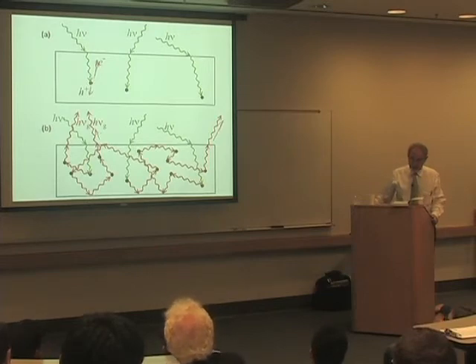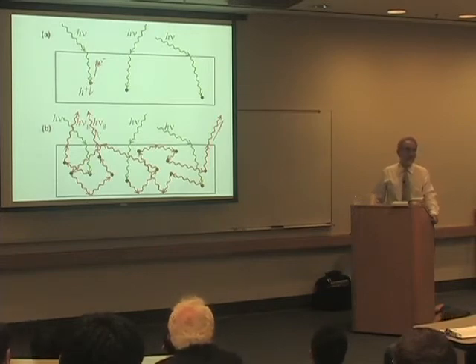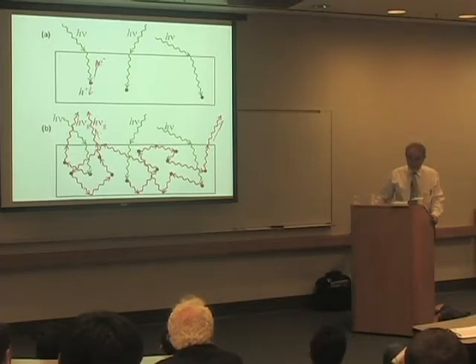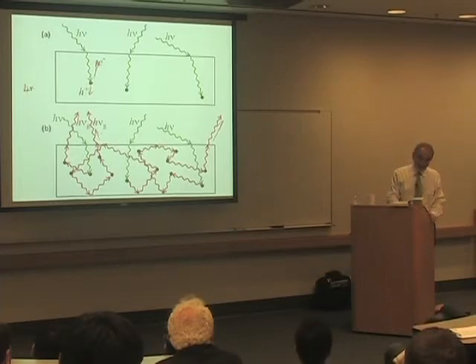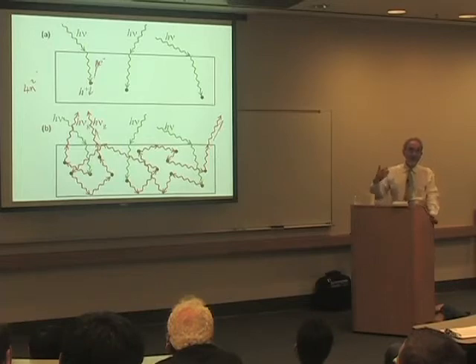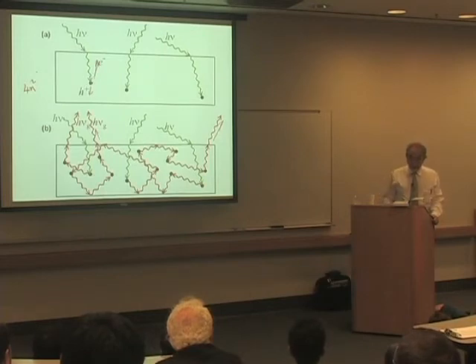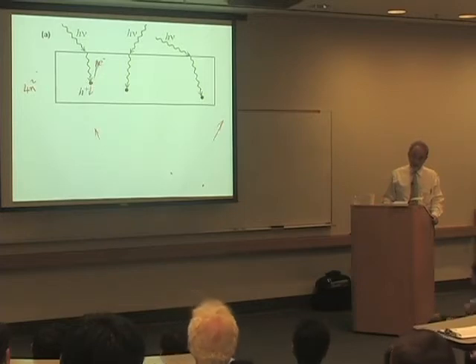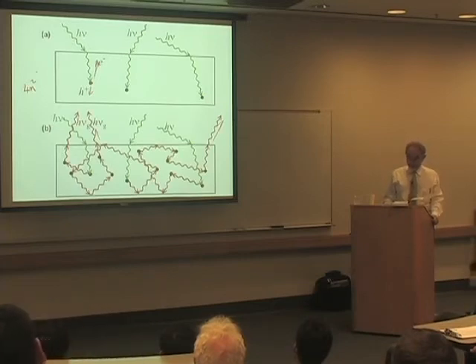And in effect, a high-efficiency solar cell has an internal photon gas of luminescent photons with an intensity that is roughly 4n² times the incident sunlight. So you could have 20, 30, 40 suns inside a one-sun solar cell. And that would be the normal operating condition if you're above 25% efficiency. So this is the world below 25% efficiency, and as you strive to go above, you need to do a great job managing the photons.